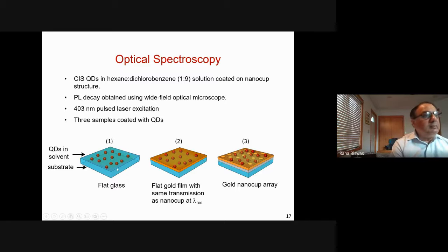Now, we fabricated 3 different samples with these quantum dots. So the control sample, the quantum dots were spin coated on flat glass. That's one. The second sample, you have a flat gold film, and then you spin coat the quantum dots. And the gold film has the same transmission as the nanocup array at this resonant wavelength. And the third one is the nanocup array that I show you. And here, when you spin coat, the quantum dots go inside the nanocups.